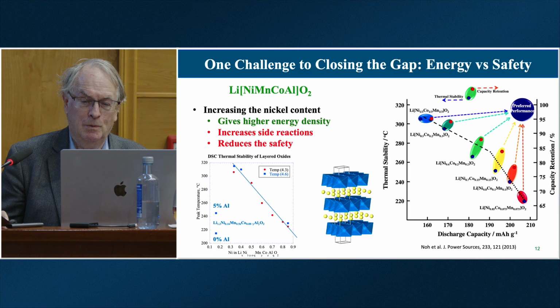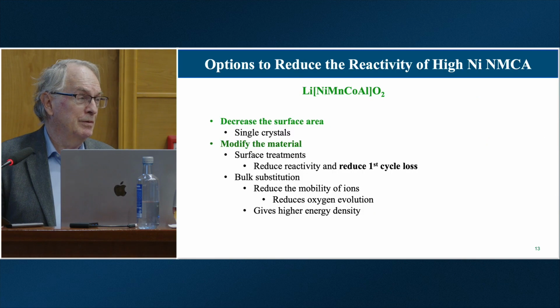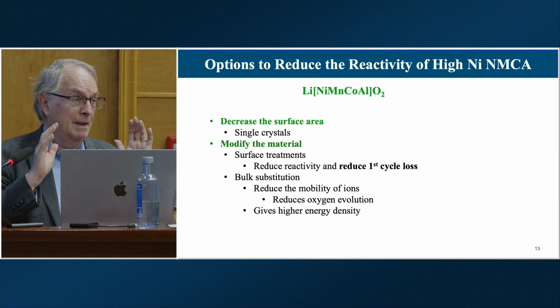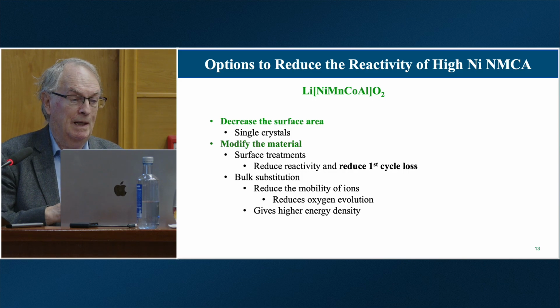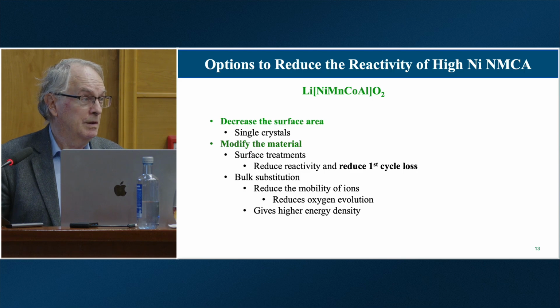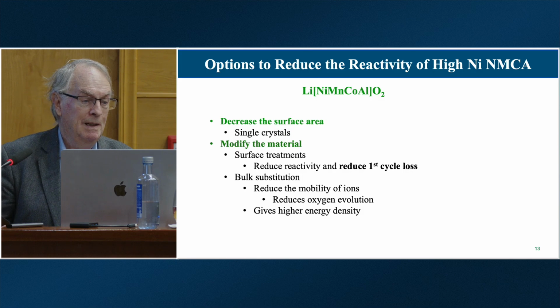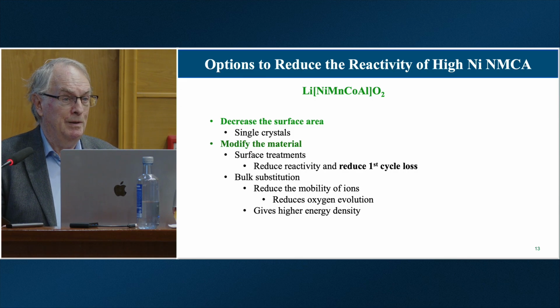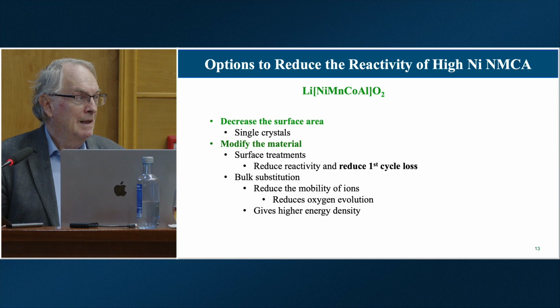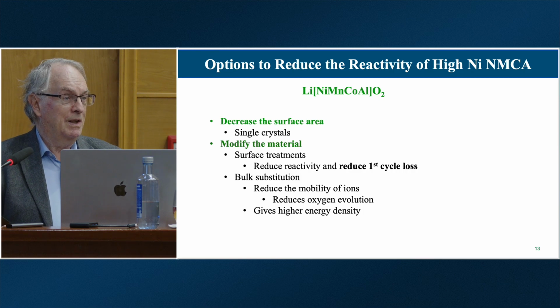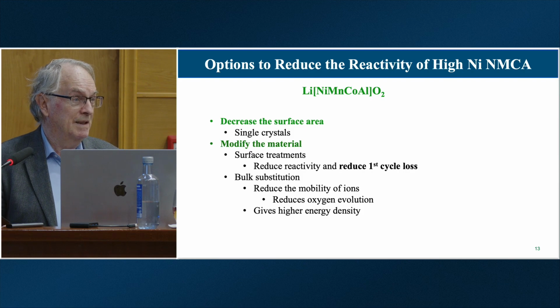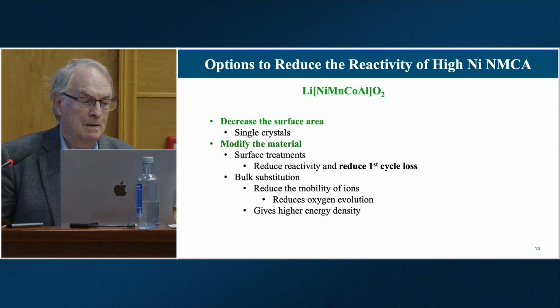So let's just look at what our options are to reduce the reactivity of these materials. As I say, we want to get as much nickel in as possible, so they can be very reactive. One thing to do is decrease the surface area. So the less surface area you have, the less reactive it will be. One option there is to go all the way to single crystals, away from those meatballs. Second way is to actually modify the materials so they're not so reactive. And by that, we don't mean we're going to change the thermodynamics, we're going to change the kinetics, so those oxygen ions cannot diffuse to the surface and be evolved there.